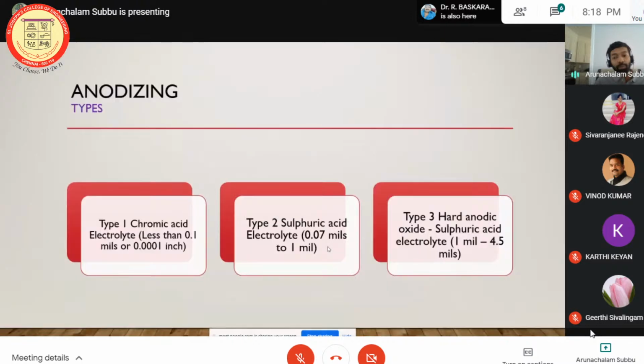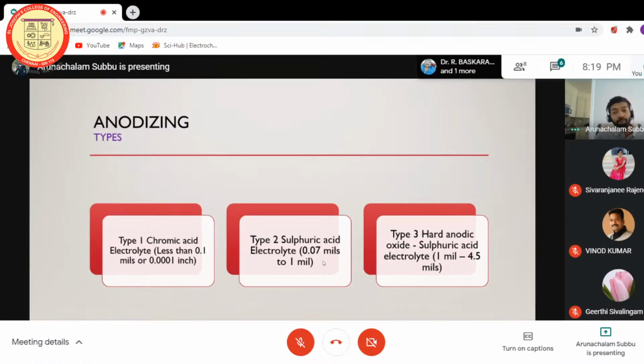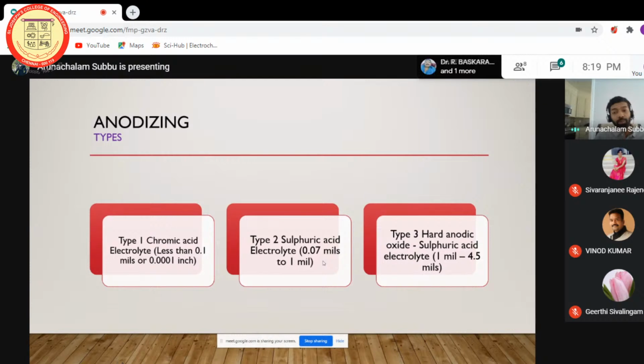Yeah, anodizing. There are three types of anodizing. The first type is where you use a chromic acid electrolyte. The second type is where you use a sulfuric acid electrolyte. The third is also a sulfuric acid electrolyte, but it's a hard coating. The first is used in electronics and similar applications because it has very little thickness, about 0.0001 inches, a very small coating. And the type two sulfuric acid electrolyte is the more widely used type, with a medium thickness coating, and type three is for extreme environmental conditions.